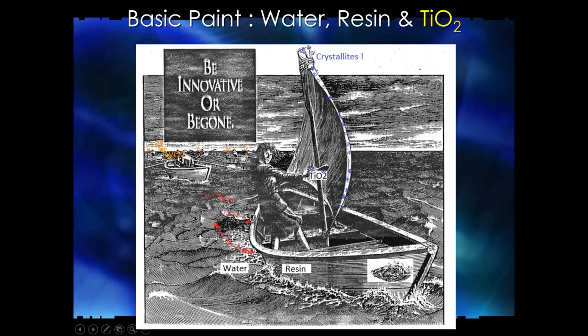Now, mysteriously, on this TiO2, there's something called crystallites on the surface. And not very many people know that almost all the titanium dioxide ever made for paint grades has an alumina surface. But alumina is not alumina is not alumina. There are 2 types of alumina on the surface. There's a boehmite alumina and there's an amorphous alumina. And then there's ratios of those things. And then there are sizes of the crystallites that are on there.